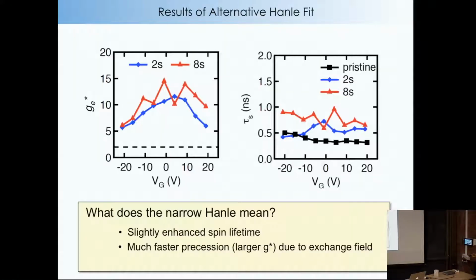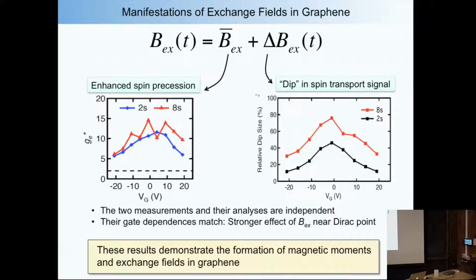Okay, so we do it, I would say, the right way, and we see G stars of about up to 14 or so. So that means the exchange field is maybe 5 times larger than the external field. But what I like about this, in the end, is that you have an exchange field here. There's an average part and there's a fluctuating part. So the average part generates the spin precession, and there's a peak near the Dirac point. Over here, on the right-hand side, you have the fluctuating part, and that's what generated the dip in the non-Hanle data. In the regular data, you had this dip, and that also has its maximum effect near the Dirac point.